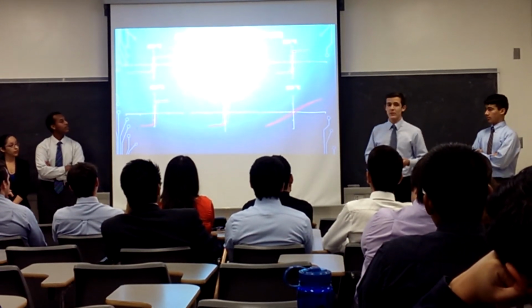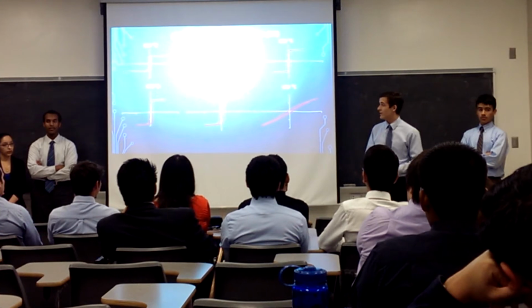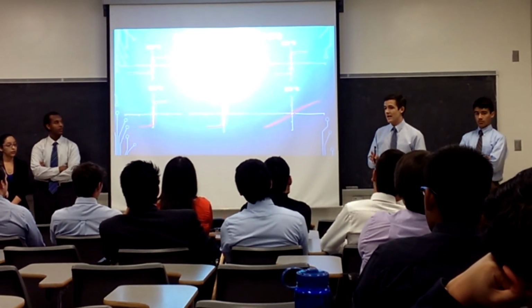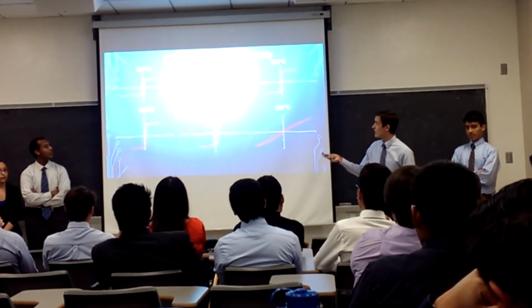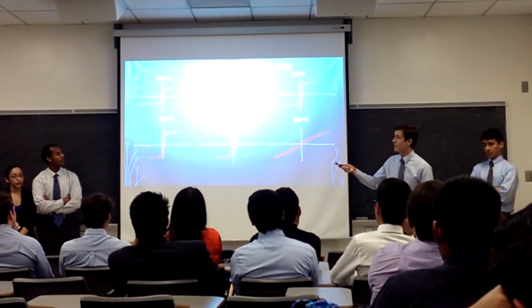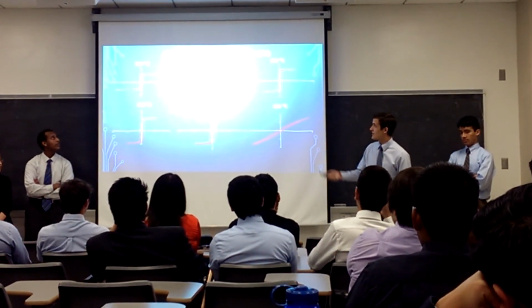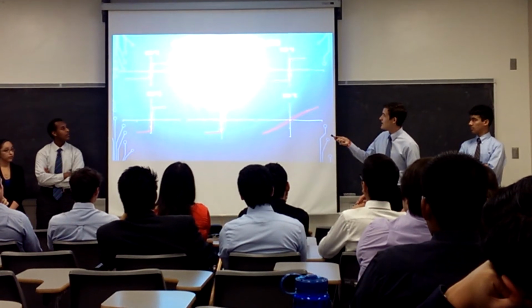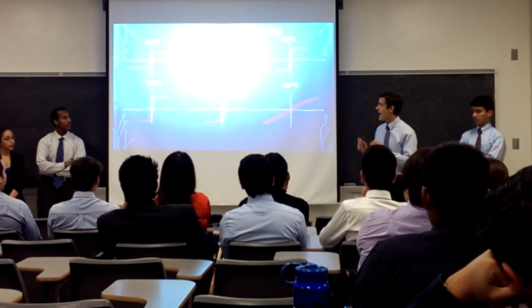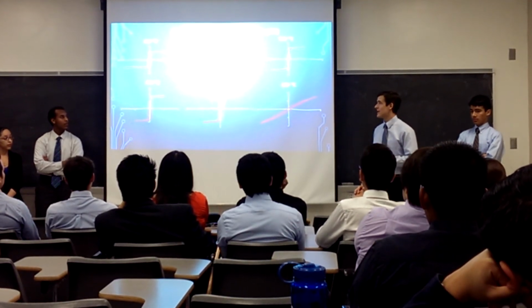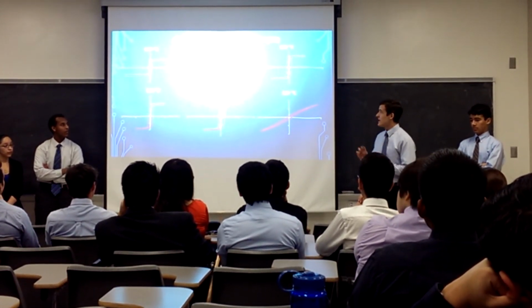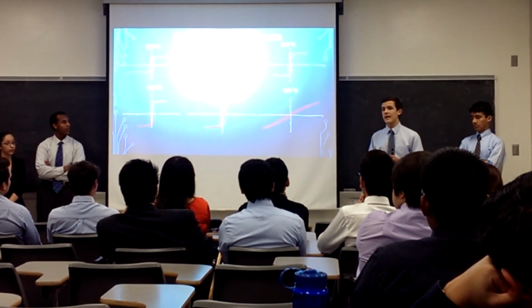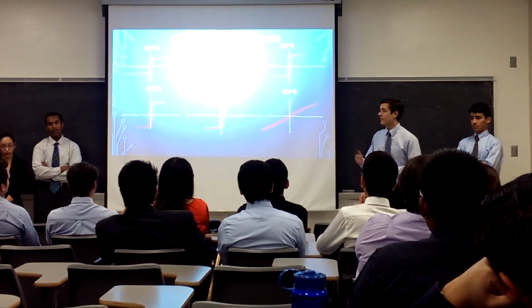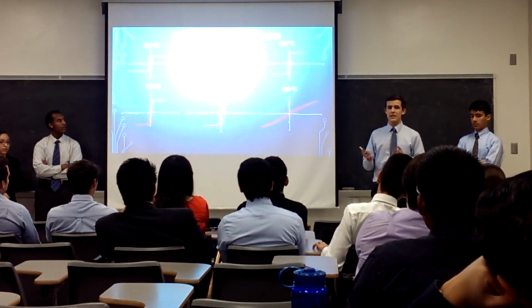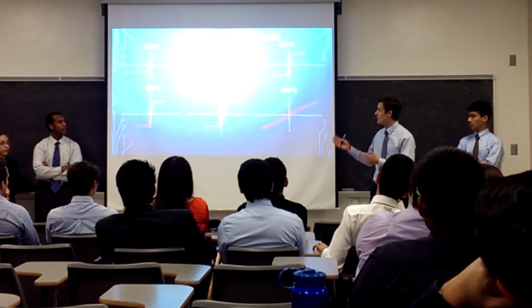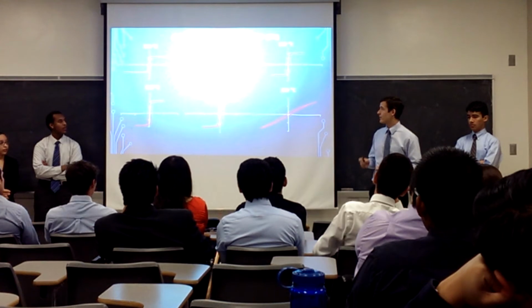So for the samples that we are working with, which were nickel and nickel oxide, the Néel temperature is 227 degrees. So if exchange bias occurs in the substance, the curve shifts to the right along the horizontal axis. So we can see that for 200 degrees Celsius, below the Néel temperature, the curve is centered at the XY intersection. For 210, we did actually see a shift to the right, which shouldn't have occurred had the sample been heated up to 210 degrees Celsius, but we have two possible explanations for this. Either because we're working with thin films on the nanoscale, the particles are so small that they're more greatly affected by thermal fluctuations, or the other reason for this misrepresentation of the trend that we should have seen is because the thermocouple didn't accurately measure the temperature.